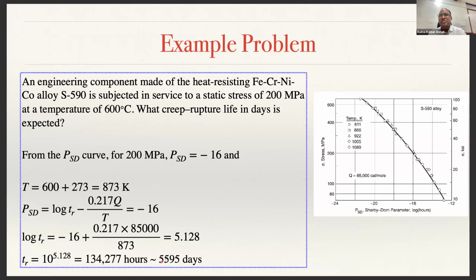134,277 hours. That means this component can be operated at that particular temperature at a static stress of this value for 5,595 days. Okay.